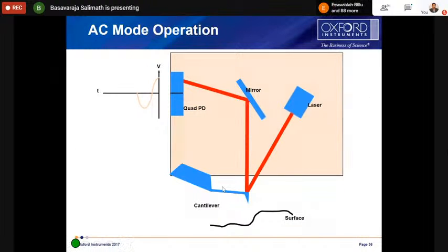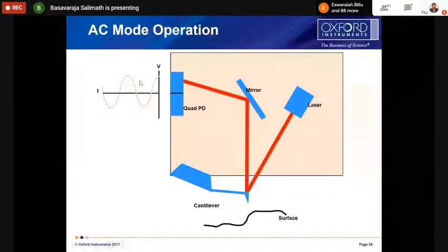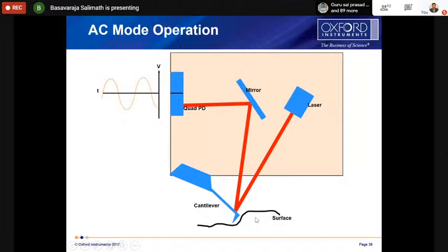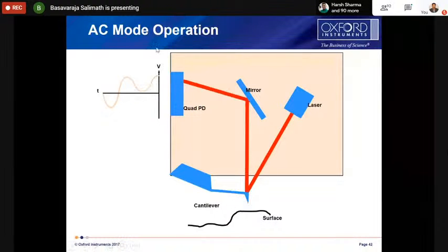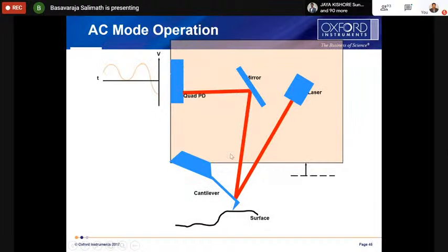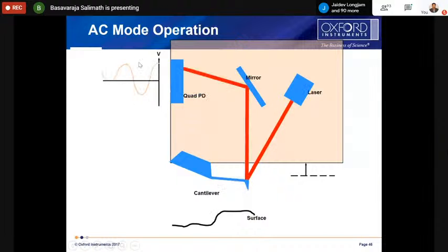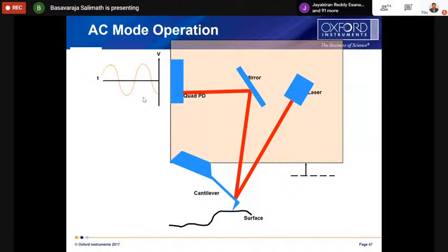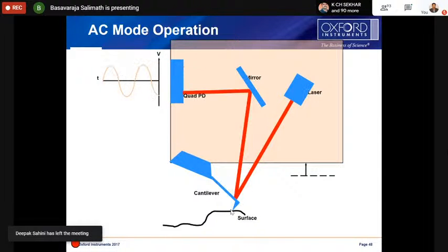You can see this is the oscillation. It has to maintain this amplitude constant. But when it goes from here to here, the amplitude becomes very small, and it has to maintain this amplitude while scanning. So it will adjust the tip height, and you can see the amplitude become bigger again, whatever it was initially. Like this, it is monitoring the amplitude of the tip oscillation, and then it gives us the images in the case of tapping mode or semi-contact mode.